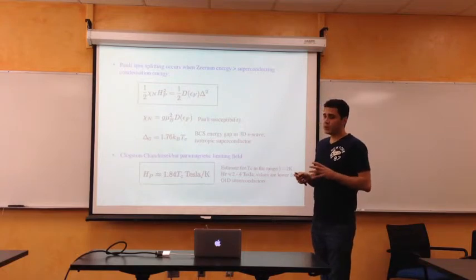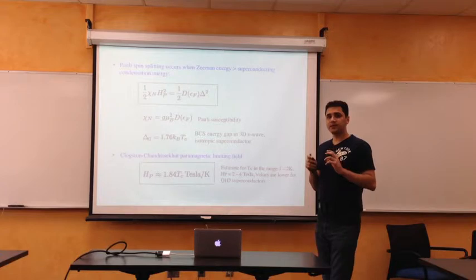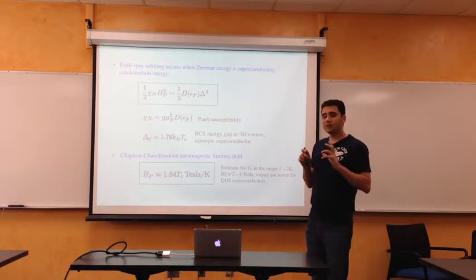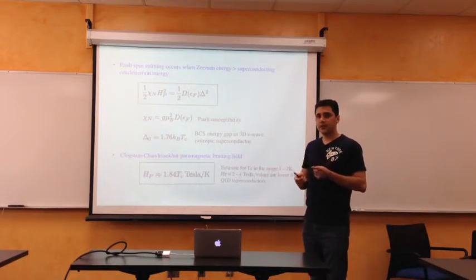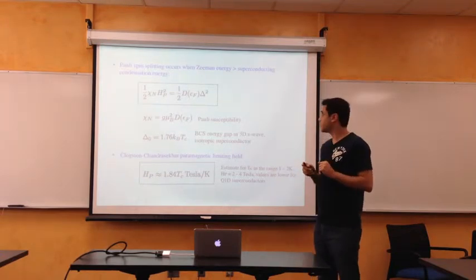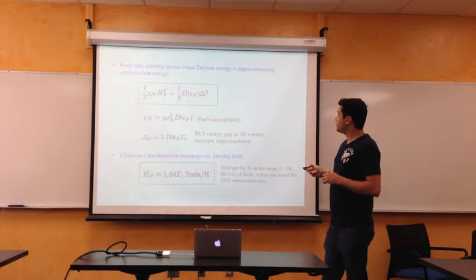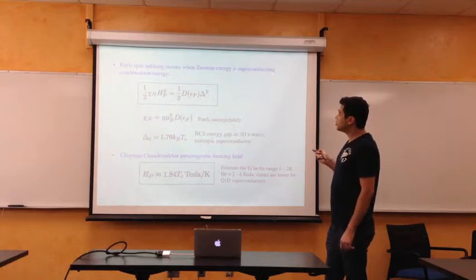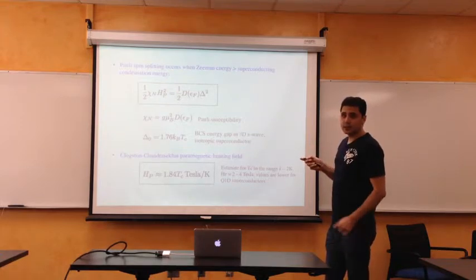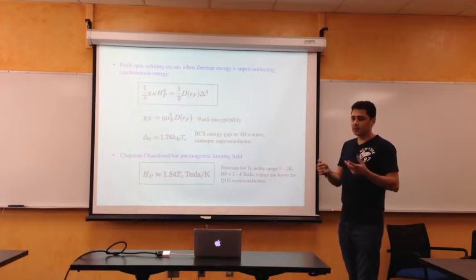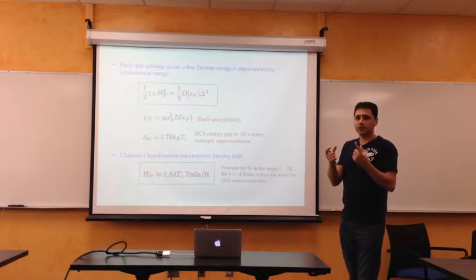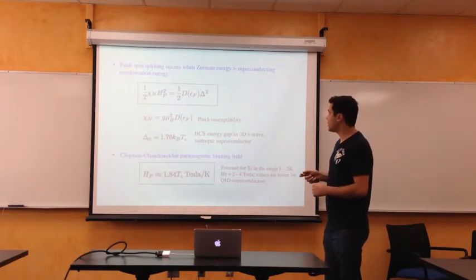So how do we actually calculate the magnetic field, the minimum value of the magnetic field that will align the spins and destroy superconductivity? We can get an estimate by setting the Zeeman energy splitting between the energy levels greater than the superconducting condensation energy, which we can think about as being the binding energy of formation of a Cooper pair.